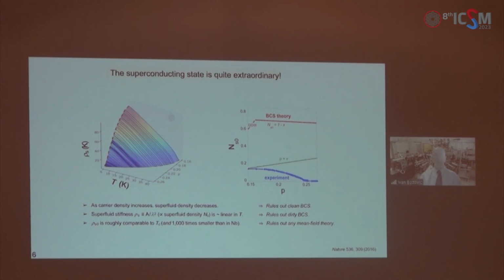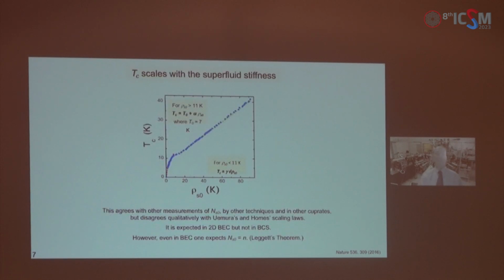Note that at the same time, the superfluid density temperature dependence remains linear all the way to Tc. And so you don't see a characteristic drop due to the closing of the superconducting gap. In fact, the more overdoped you go, the more accurately linear it gets, in some cases down to less than 1 Kelvin. And this is what one should expect from an ultra-clean d-wave superconductor. Now, I'll get back to this point later on.